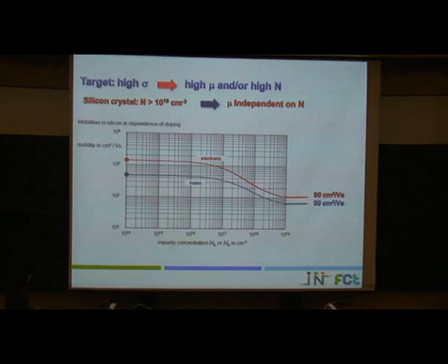So of course, our target is to have a high conductivity or a low resistivity, and of course a high mobility and/or a high carrier concentration, because you know that the conductivity is n times q multiplied by the mobility. For example, this is a typical graph, this one is for silicon, which is very well known. Here we present the mobility as a function of the impurity concentration. What happens is that if we increase the doping, the mobility starts to decrease. And for high levels of doping, around 10 to the 19, the electron mobility is around 90 square centimeters